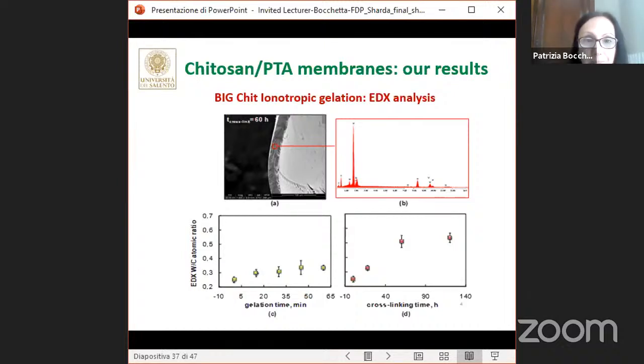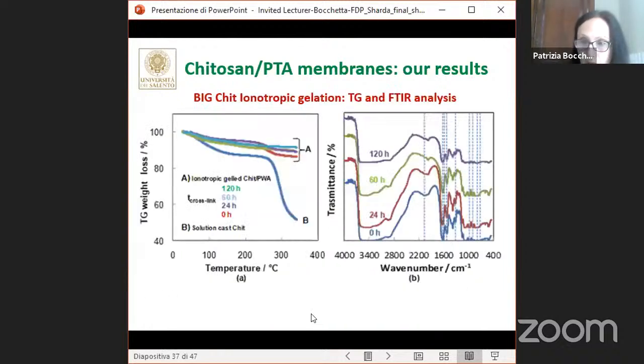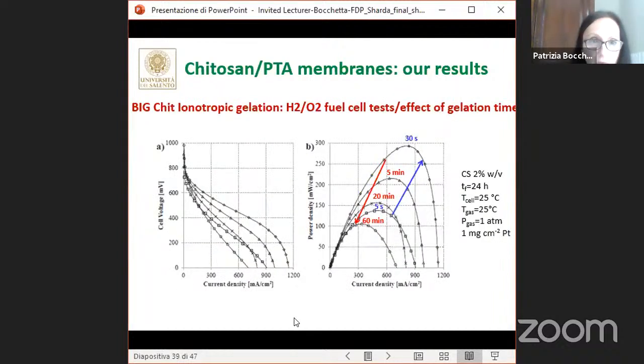Also, we can see that in the post-cross-linking, the ratio strongly increases, going from as formed to 60 hours of post-cross-linking treatment, and afterward it remains quite constant. So we have that 60 hours of post-immersion is the time necessary to have complete cross-linking of chitosan. I am probably over the time, so I go fast.